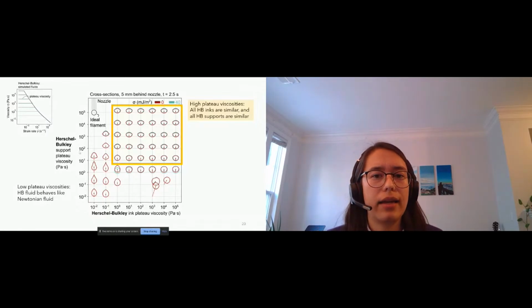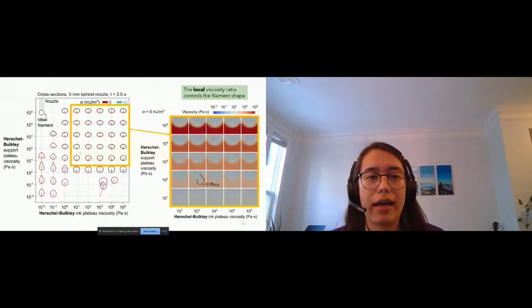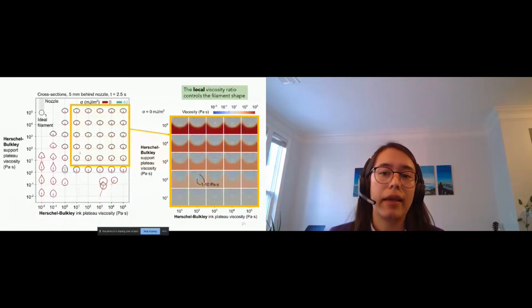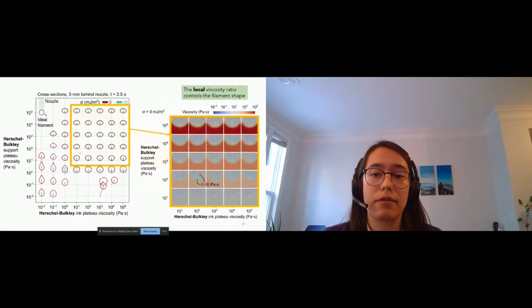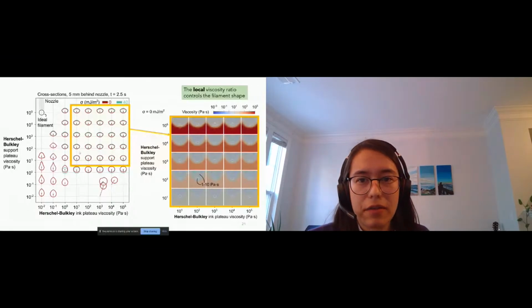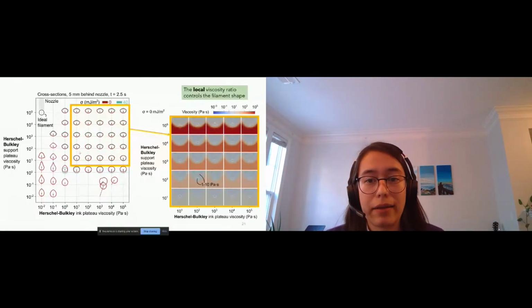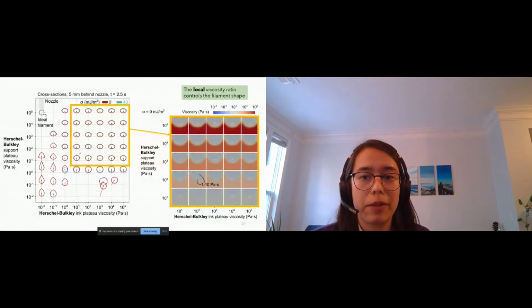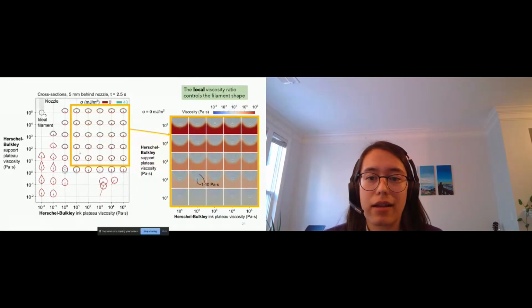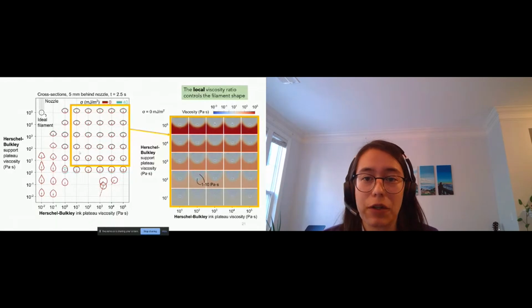So we can identify why that happens by looking at slices of our simulation. So here I've sliced through the bath and the color is indicating the viscosity of the fluid. So in the center of these plots, you can see there's this sort of white outline. That's the outline of the filament. So inside the filament, the viscosity is about 1 to 10 Pascal seconds for all of these.